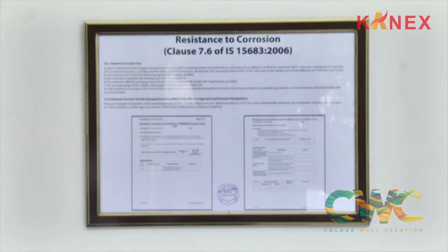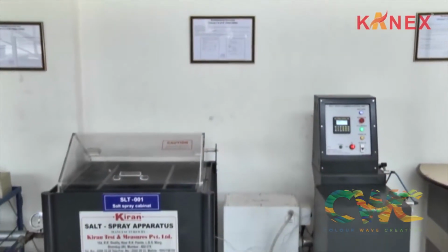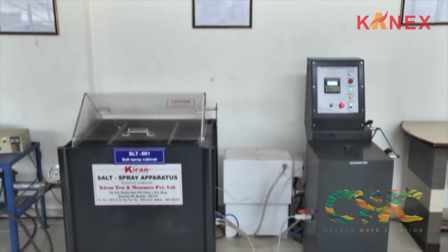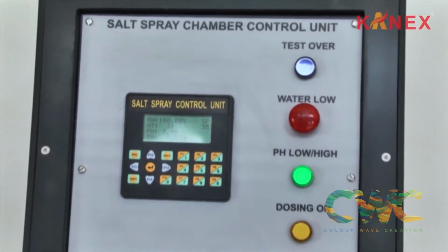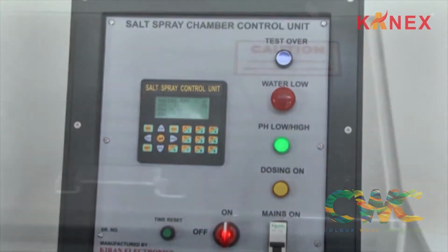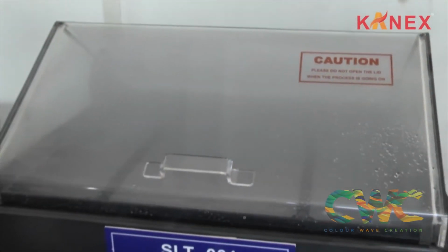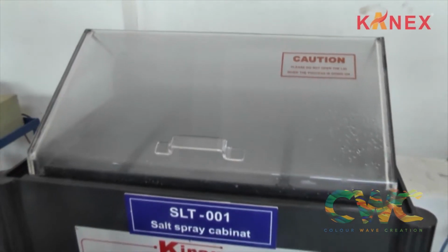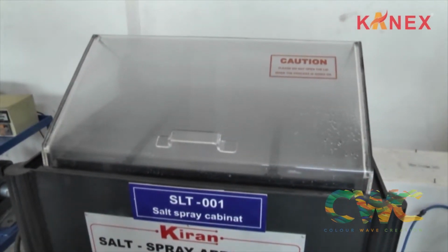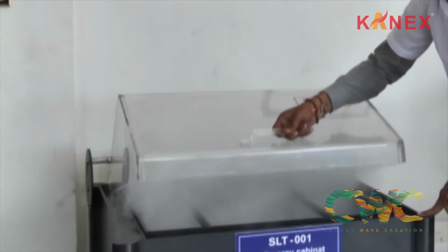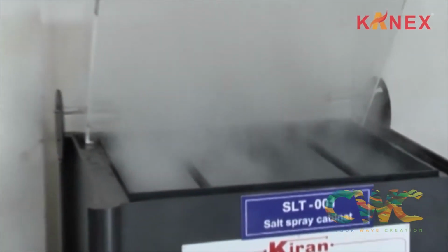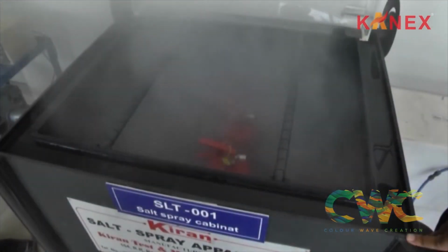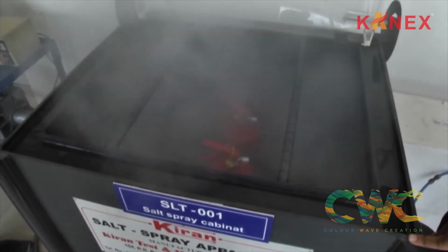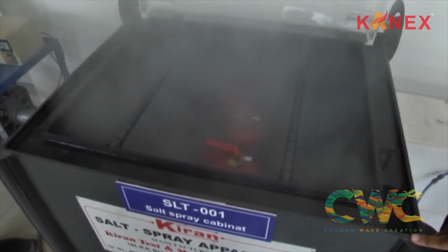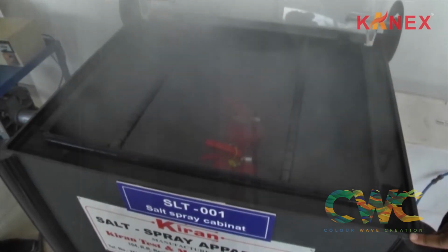External corrosion test. The salt spray chamber is built to meet ASTM B117 and IS 6910 standard requirements. A fully charged extinguisher assembly shall be conditioned in the chamber for 240 hours. Following 24 hours of drying, the extinguisher will be checked for mechanical operation of all parts, pressure gauge for function and water tightness, corrosion of any metal parts, and finally for normal operation.